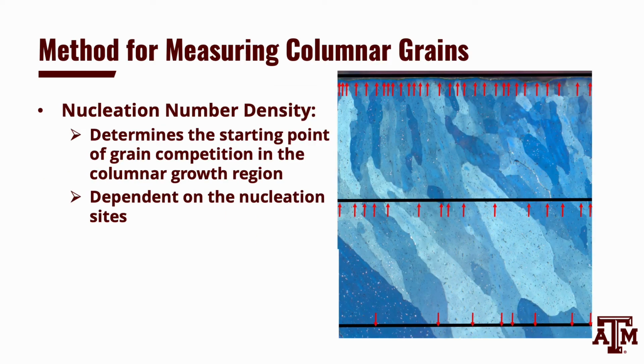The method for measuring columnar grains is called nucleation number density. The grain density is determined by the nucleation reaction. In the figure presented, an example of grain density counting of grains along the cast. Each arrow corresponds to the intersection of unique grains, parallel to the cast. The grains on the edge of the cast are to be counted if they intersect with the cast interface.